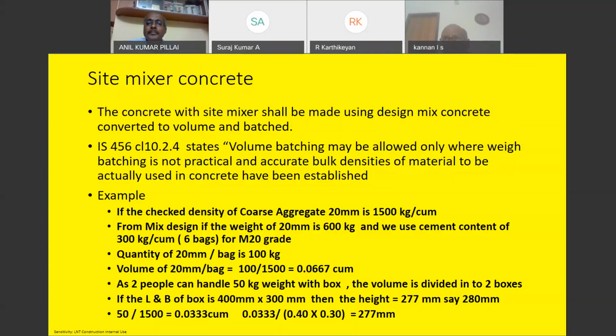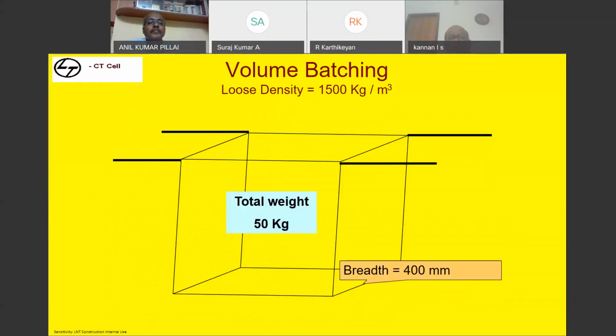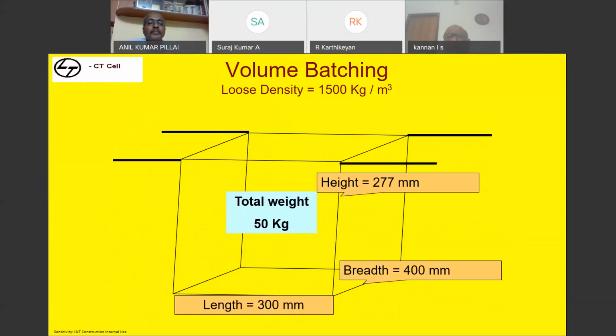Instead of making 1.25 CFT boxes, you are going to make volumetric boxes equivalent to the volume of 50 kg of aggregate. So 50 kg divided by 1500 comes to 0.033 cubic meter. The box size can be, for length and breadth, 400 by 300, so the height should be 277. If you are able to make a box like this for 50 kg, 300 by 400 with a height of 277, and fill the aggregate up to the top without any overflow, leveled, it is going to weigh exactly 50 kg of material.